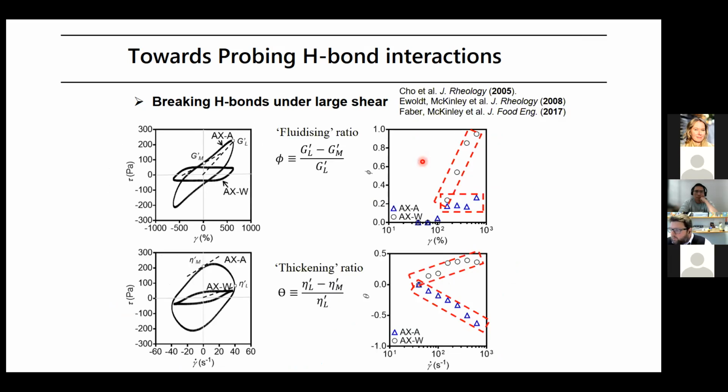What was interesting is that for the different fractions, this behavior is totally different, because for the water-soluble fraction, you have a huge thinning effect. As soon as you apply shear, there is a thinning effect. But for the alkaline soluble fraction, by contrast, you observe a huge thickening effect. You start shearing it and it resists the shear. So essentially, the more you shear, the more the gel consolidates. So this is a totally different response to the shear and to the deformation.